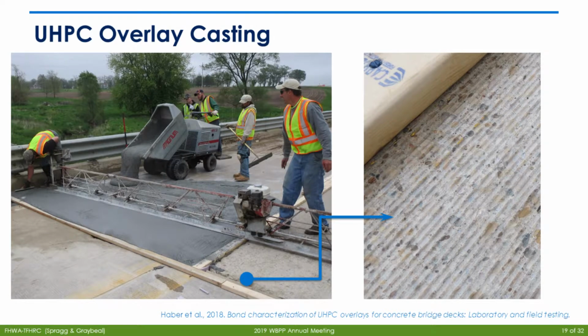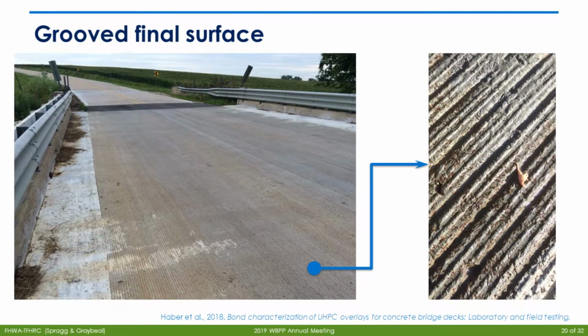They did do hydromilling on this deck, so you can see what this surface profile looked like, and we'll see some more pictures under the microscope in the next couple slides. And then this is what the overlay casting looked like. So you would have this vibratory Bidwell that they were just pouring the overlay and then pulling it along behind them. And then this is what the final product looked like, again with a grind and groove on the surface.